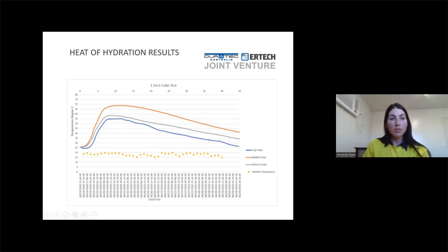So the trial was successful, with a max temperature of 68 degrees Celsius. The max internal temperature differential was 13.9 degrees Celsius, our ambient temperature at that time was 19.3 degrees Celsius, and our slump was 160. The trial had hessian and sprinklers on, reflective insulation, and tarpaulin on top for the curing period. This was undertaken on the 24th of June, and all this was downloaded after 120 hours.